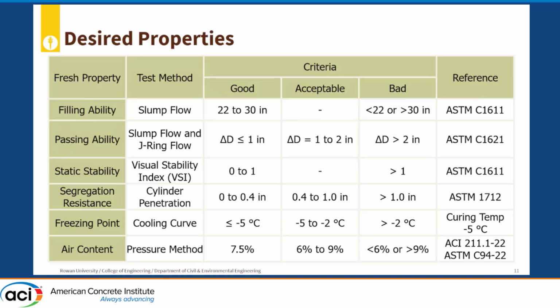Filling ability is based on the slump flow test, and the spread diameter should be between 22 to 30 inches. Passing ability is the difference in spread diameter between the slump flow test and the J-ring flow test, which is the one with the J-ring or the blocking. A difference in spread diameter should be up to 1 inch to say that there is no visible blocking, or up to 2 inches to say that there is noticeable blocking but still acceptable blocking.